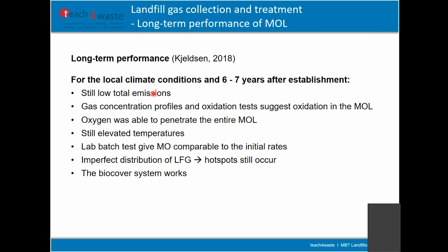So still low emissions. They show the profiles, they have determined that they still have oxidation in the methane oxidation layer. Oxygen is still diffusing inside of this layer. They have elevated temperatures, which also shows that it is working well. And they have made some tests of the soil materials they've placed in the biofilter, and they are showing that compared to the values at the beginning, it is working quite well. And they still have problems with hotspots.